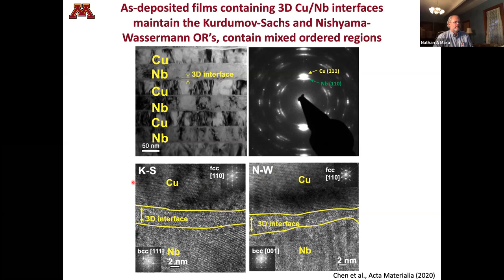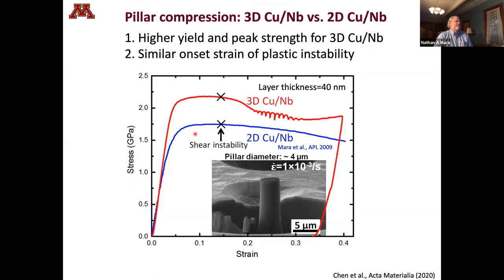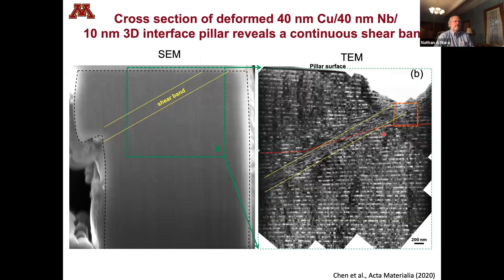Now, if you stress these, what do they look like? So here's our 2D case from what I showed earlier. You add 3D interfaces, the same pure layer thickness, and strength goes up by about a factor of 25% or so. You see very different kind of behavior here in micropillar compression. If we were to section our deformed pillar, what's it look like? Well, again, you see this shear band, right? So you can see that in SEM here.